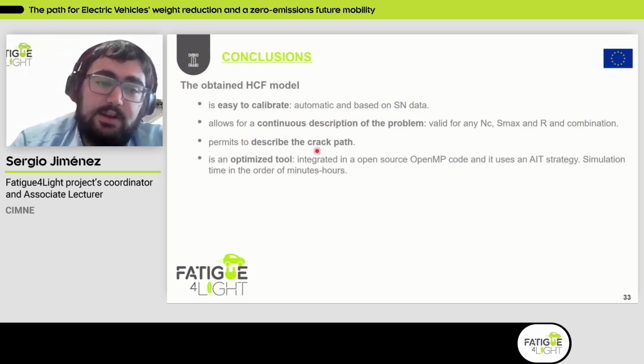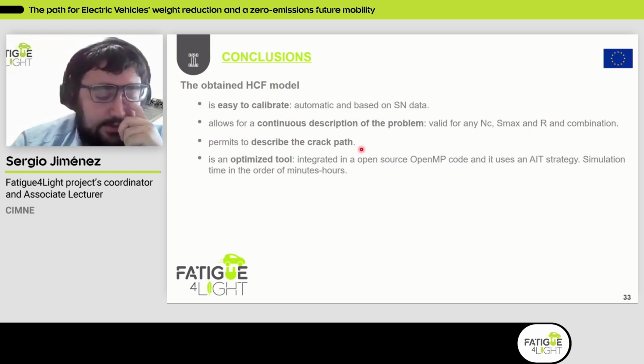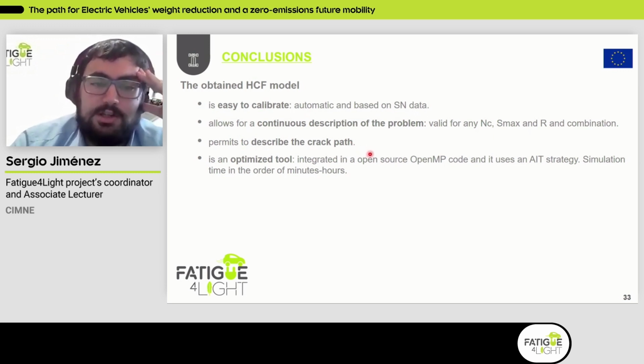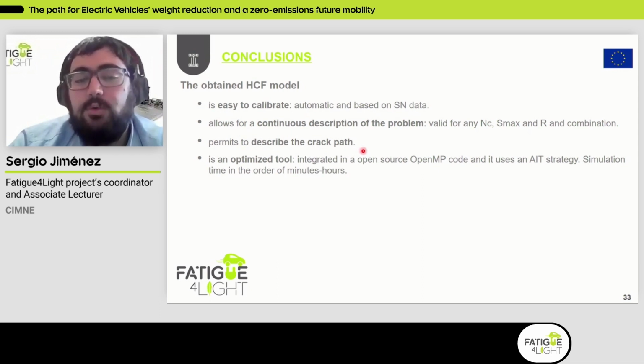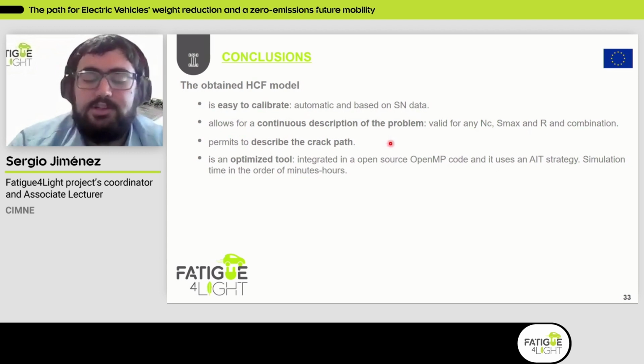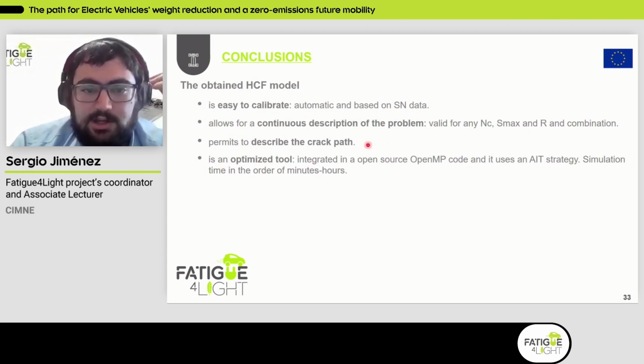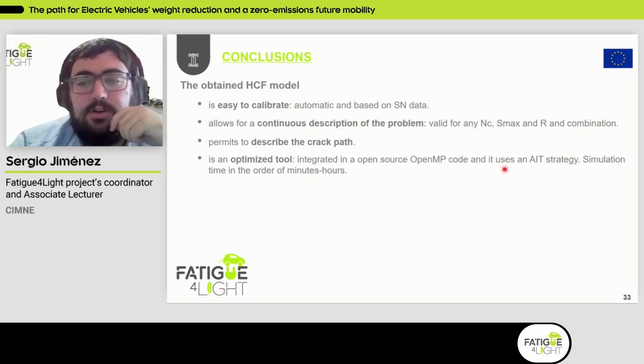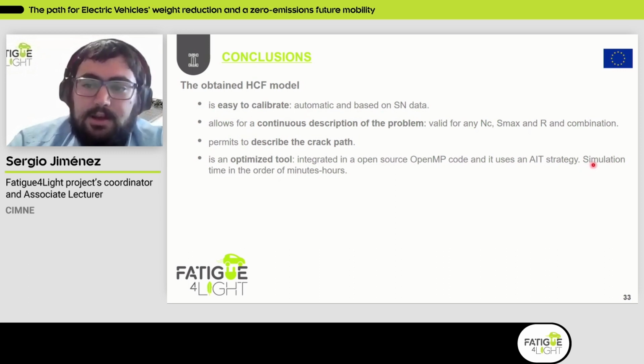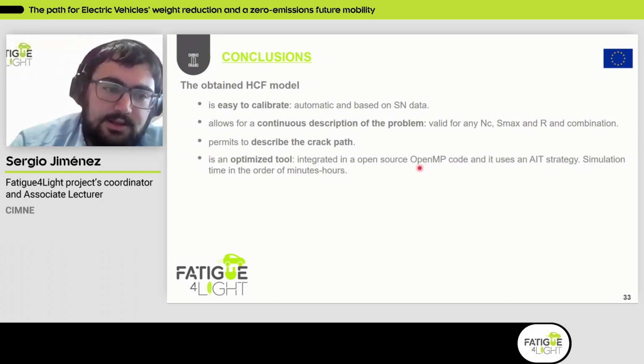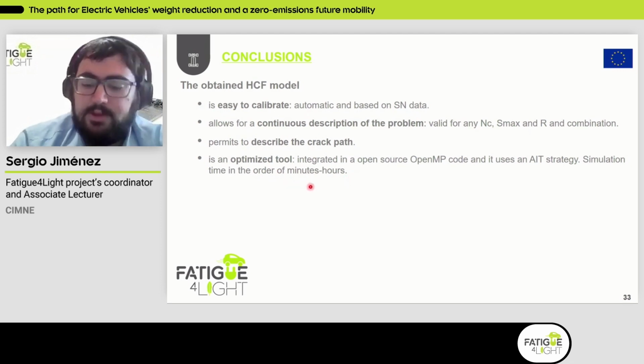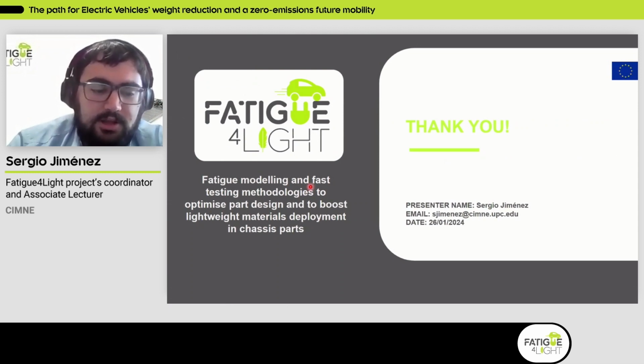It also allows describing the crack path, which usually cannot be done in commercial codes. And also good news is that we can do this not only at coupon level, but also at demonstrator level and, in general, in any general model, because it's an inherent property of the model that we built. And then just to mention that this is an optimized tool. It's been integrated in an open source parallelized code, and we've also included an advance-in-time strategy together with the model. The simulations that I was showing previously are in the order of minutes or hours at most, so really competitive in terms of time. So thank you all, and I will be glad to answer your questions after my colleagues' sessions.